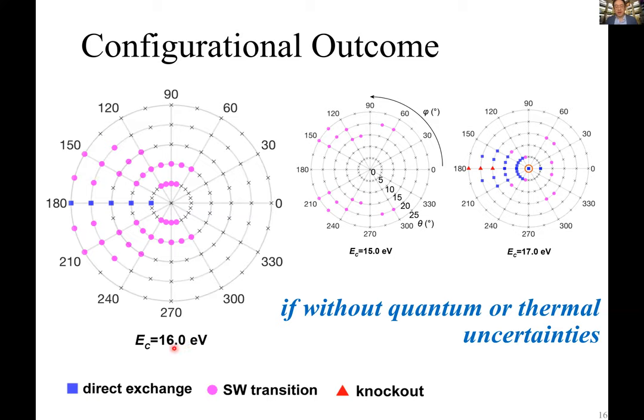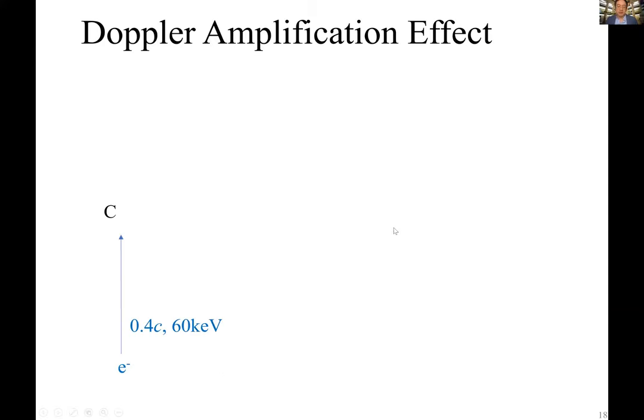So if we have 16 electron volt energy on the carbon, we get these two outcomes as a function of the direction of the momentum. But if it's a lower energy, then no 180 degree rotation. And if it's 17 electron volt, then we also get knockouts here. So you see that it's quite sensitive to the energy, to within 1 electron volt. And one assumption in this plot is we assume the carbon has no initial thermal momentum, also no quantum velocity. But that turned out to actually not be a good approximation.